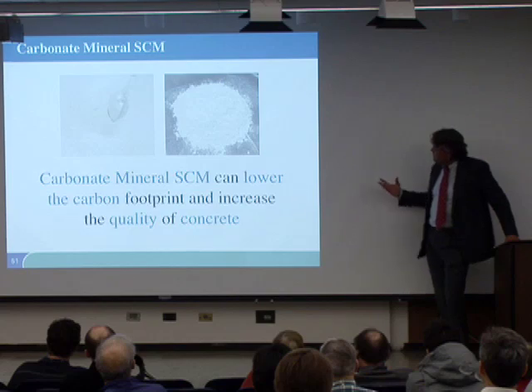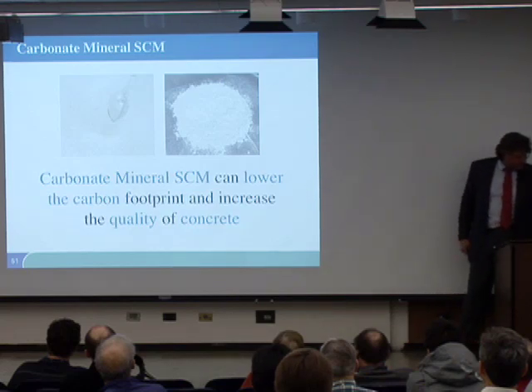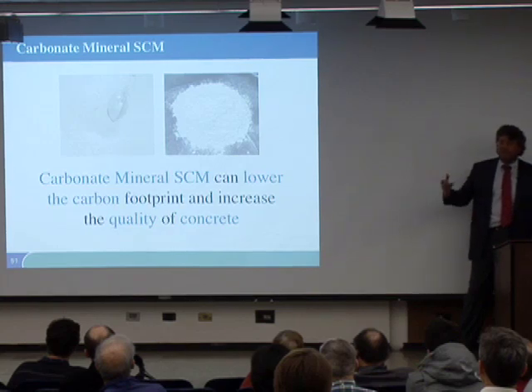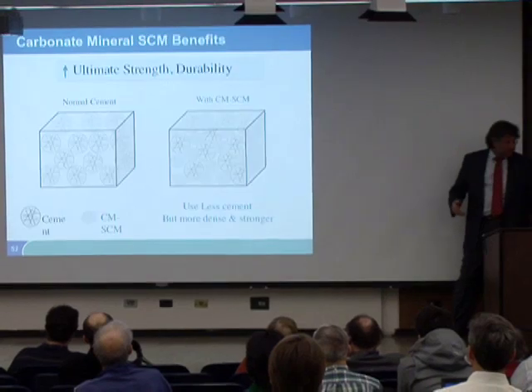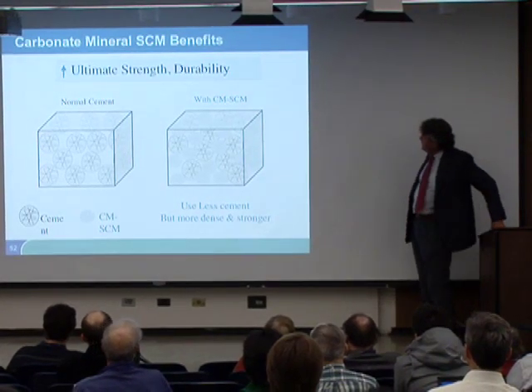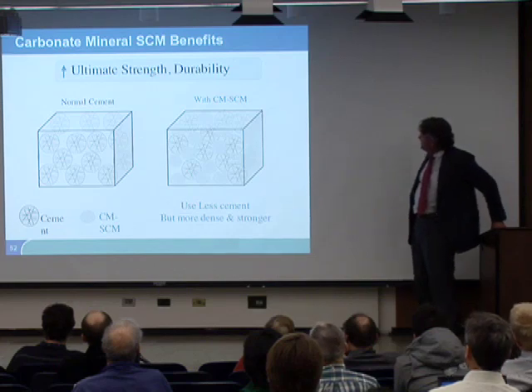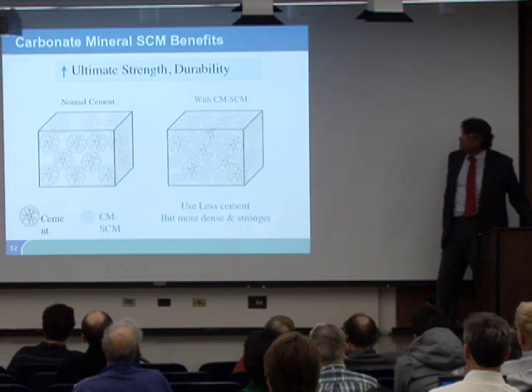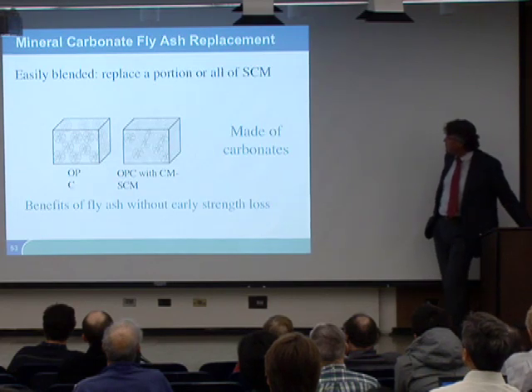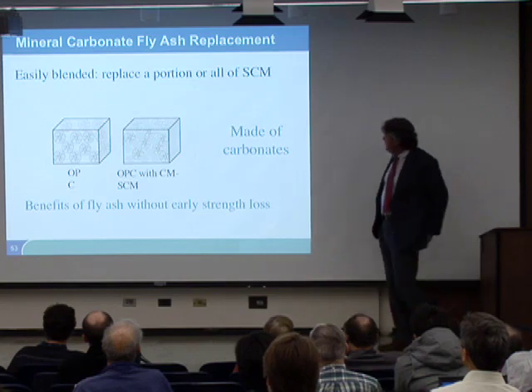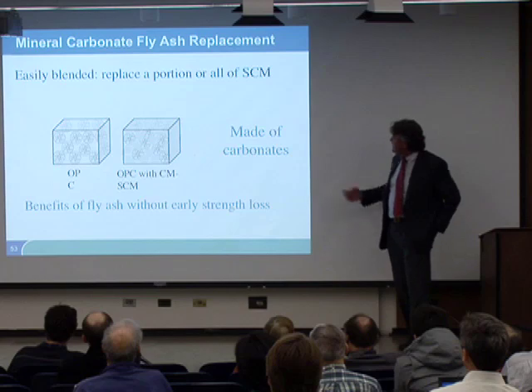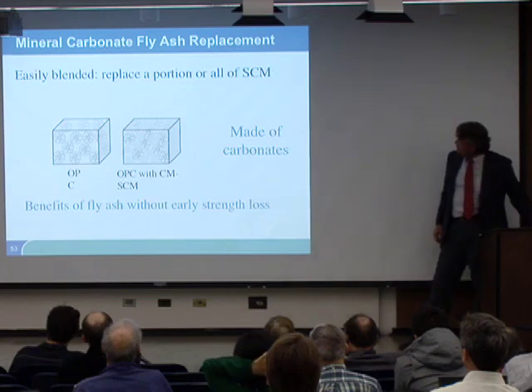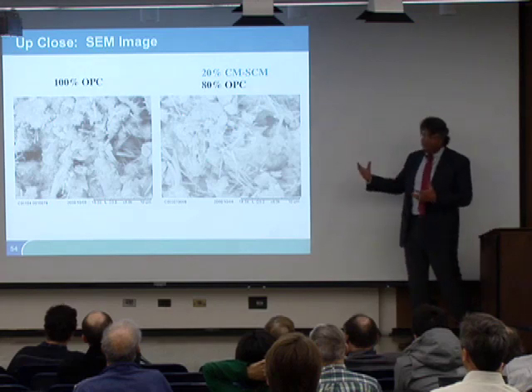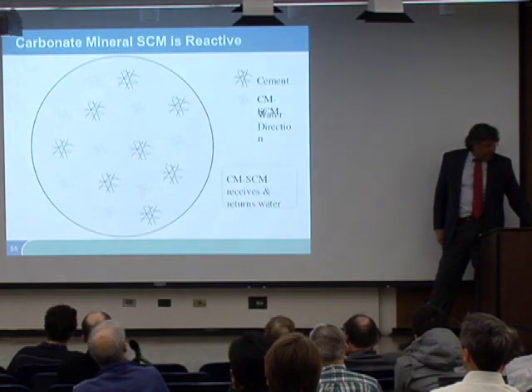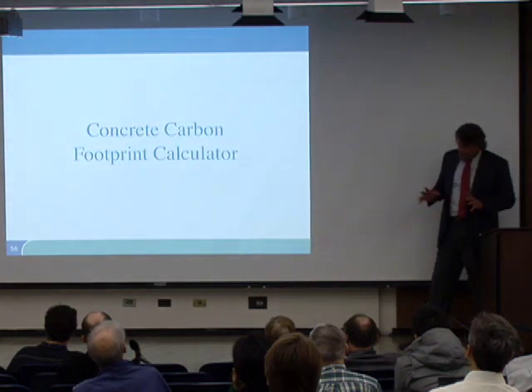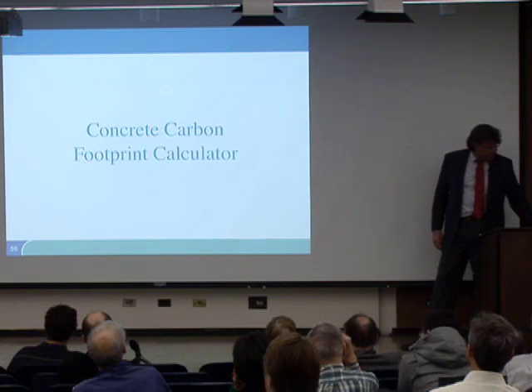The supplementary cementitious materials just look like cement. The Calera one is white, so when it's combined into Portland cement, which is gray, it gets sort of milky in color. And the way they work is you put them into the cement matrix, and it's a way to increase the strength and durability in addition to lowering the carbon footprint. So here are some blends of ordinary Portland cement that have the supplementary cementitious material in them, and they look pretty similar on a microstructural basis, and grow in and strengthen the matrix.